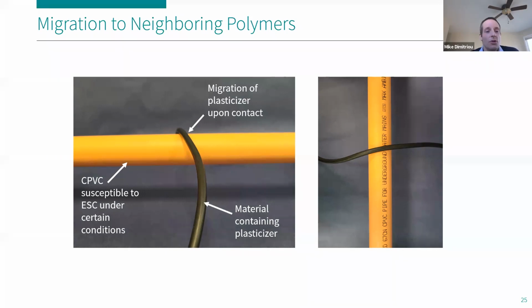In a given scenario, you may have a situation where cables or wiring becomes in contact with CPVC. And in the left image, what you can see is there is contact right at the top of this pipe. And the cable or wiring, which has insulation that is flexible, typically contains a good deal of plasticizer. And now you have introduced a route for plasticizer to migrate from the cable into the CPVC.